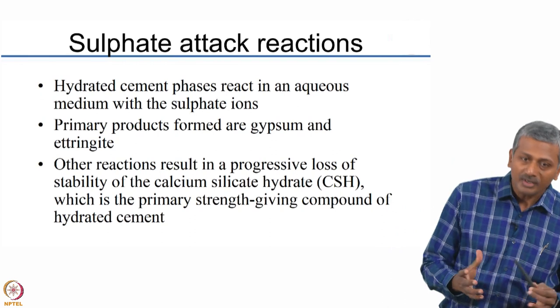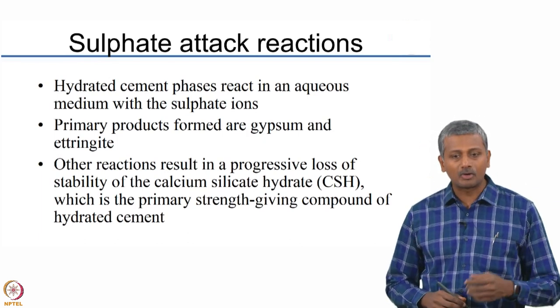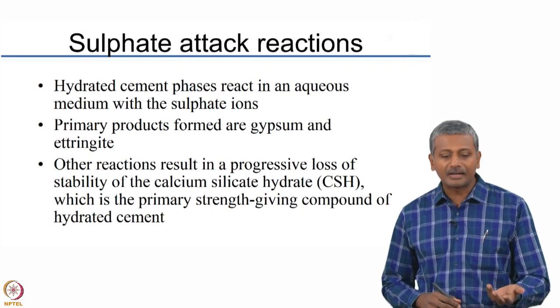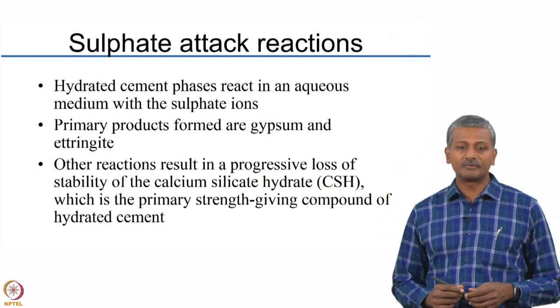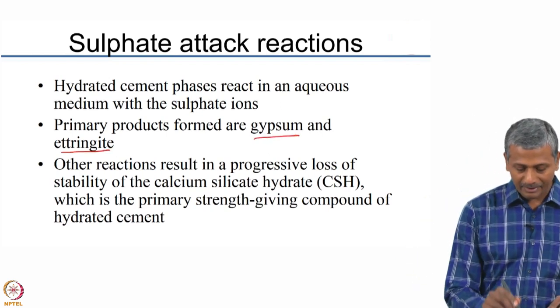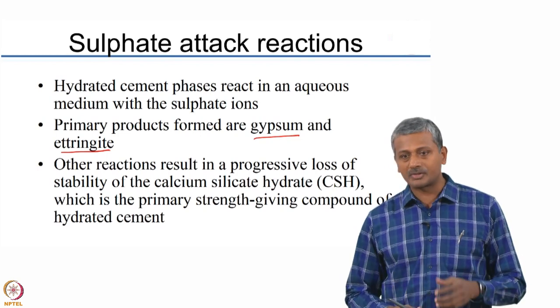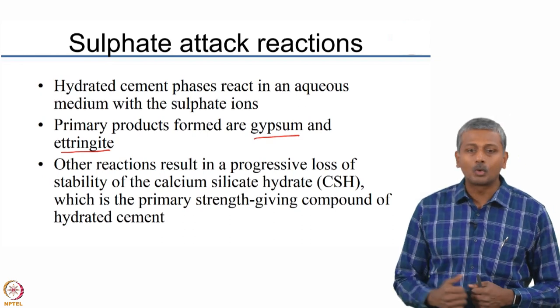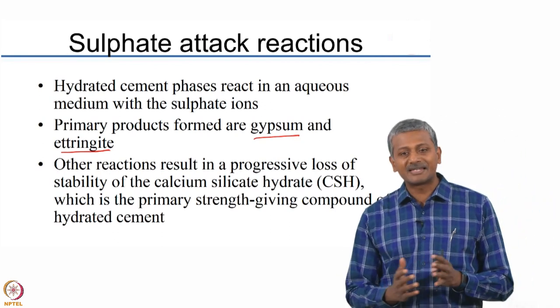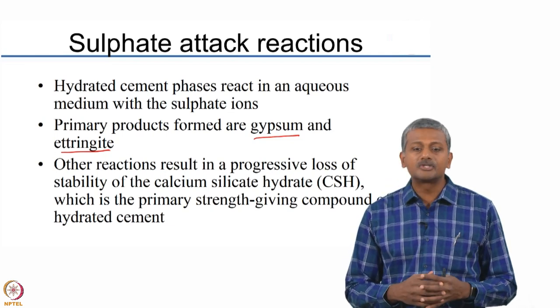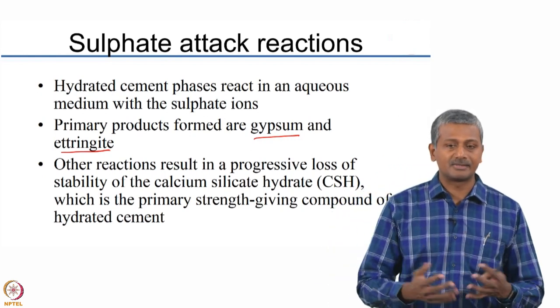The reactions that lead to products causing harm involve hydrated cement phases — calcium hydroxide, calcium silicate hydrate, and calcium aluminates — reacting with sulphate ions from the external environment in an aqueous medium. Water is absolutely essential. The primary products that form are gypsum and ettringite. Cement originally has gypsum in its formulation to control the reaction of aluminates and bring about controlled setting. Ettringite forms in the early stages of cement hydration; in the long term, excess aluminates convert this ettringite to monosulphate. When external sulphate attack occurs, the external sulphate reacts with the monosulphate and re-crystallizes ettringite.